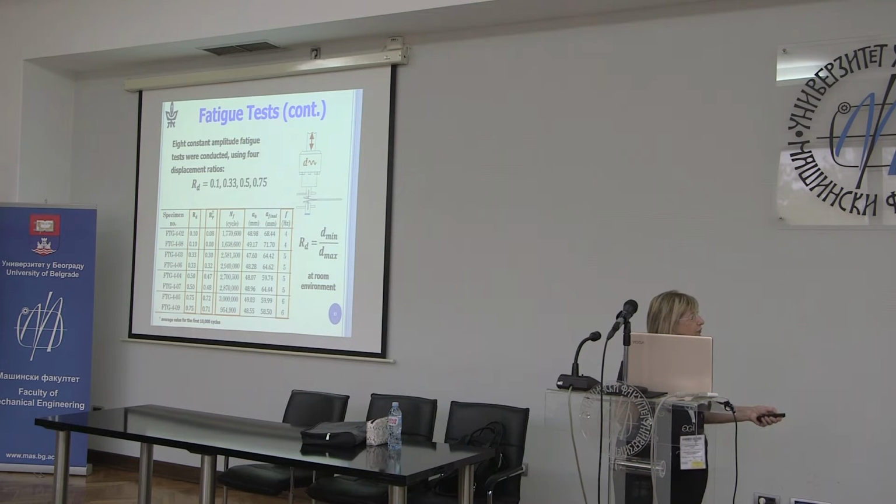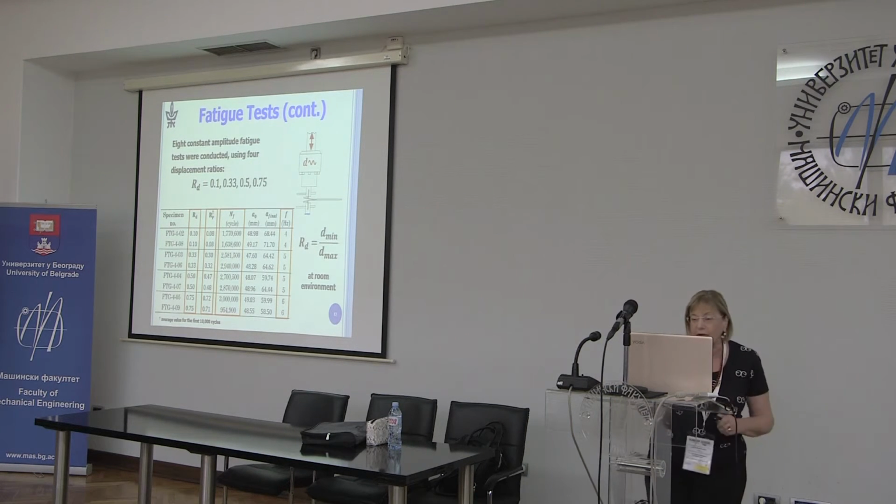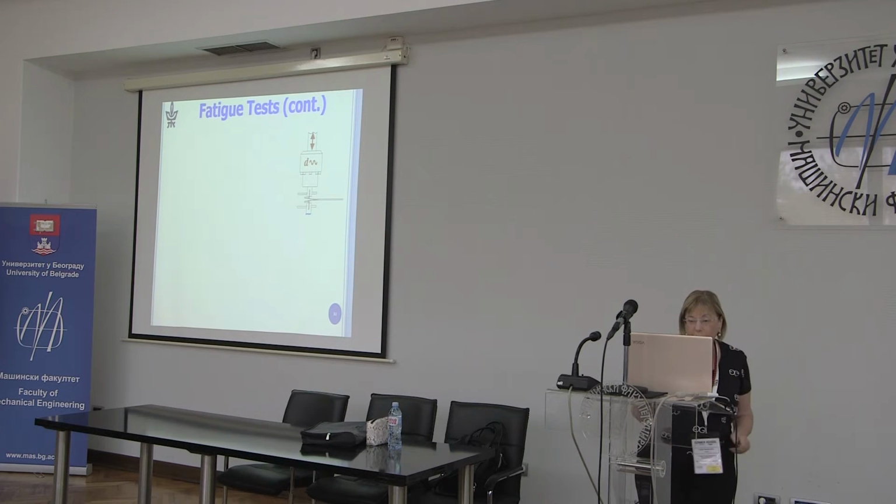The higher the frequency, the shorter the number of days, but the higher the amplitude, the lower the frequency has to be. Otherwise, you start hearing lots of noise in your machine. So we went from 4 hertz to 6 hertz.